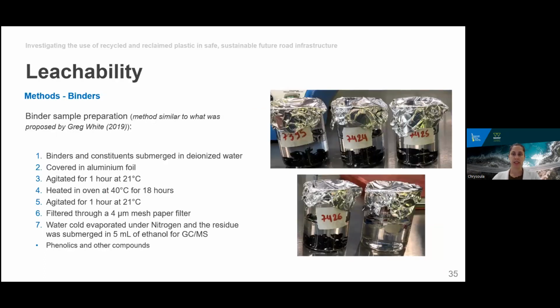To assess the potential release of leachates, we tried a couple of different things, as said. Firstly, we tried to assess leachates from the binder in a method similar to what was described by Greg White. We submerged the binders in deionized water and covered with aluminium foil, and then agitated using a magnetic stirrer at ambient temperature. Then we placed them in the oven at 40 degrees Celsius for 18 hours, and then repeated that agitation process for another hour. Once we finished with the exposure, we filtered the potentially contaminated deionized water through a 4 micrometer mesh filter. The water was then cold evaporated under nitrogen, and the residue was submerged in 5 milliliters of ethanol and prepared for GCMS.